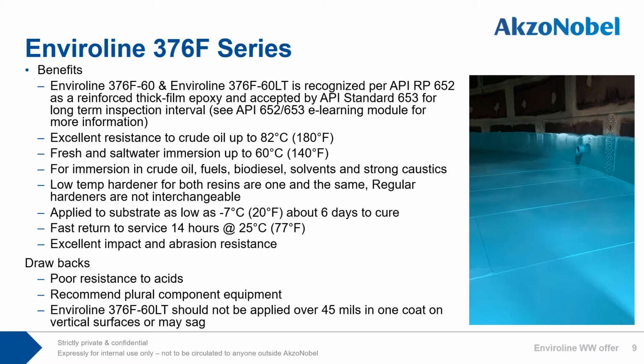I am not aware of another product with a faster cure for hydrocarbon immersion service in this industry, or one that can cure as low as -7 C. Excellent impact and abrasion resistance. The drawbacks are poor resistance to acids, and plural component equipment is recommended; however, it can be applied with single leg airless equipment and an experienced crew. Enviroline 376F60LT should not be applied over 45 mils in one coat on vertical surfaces or it may sag.